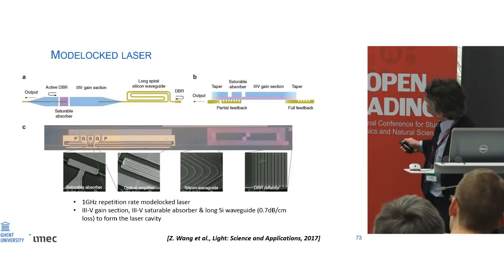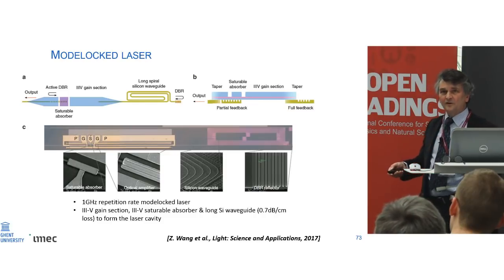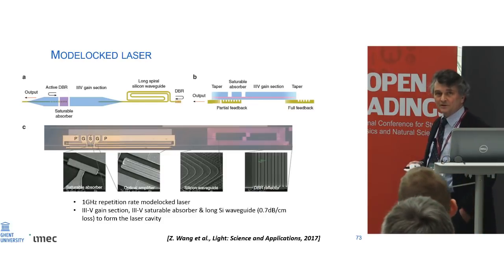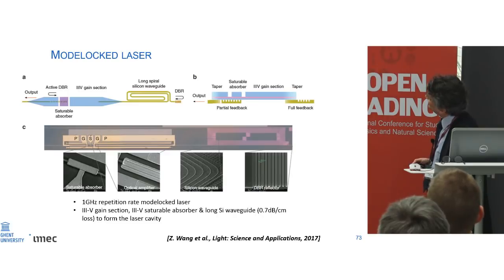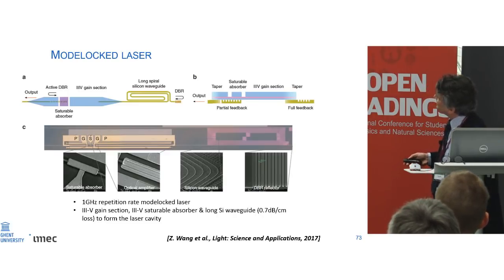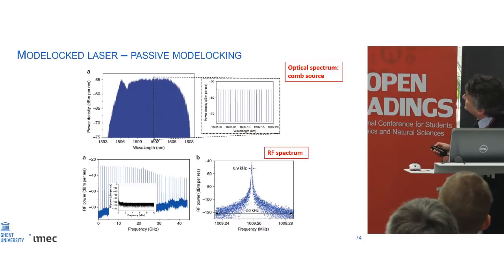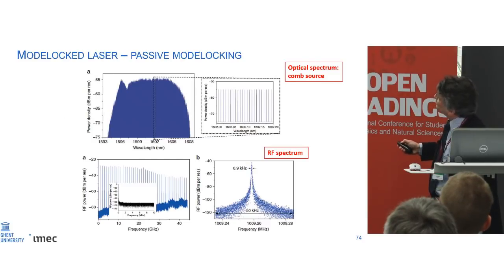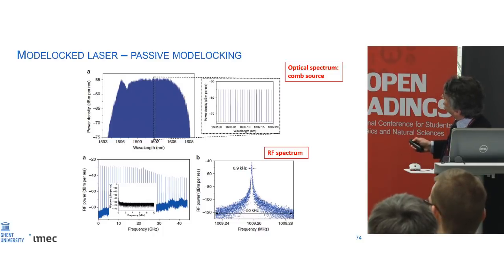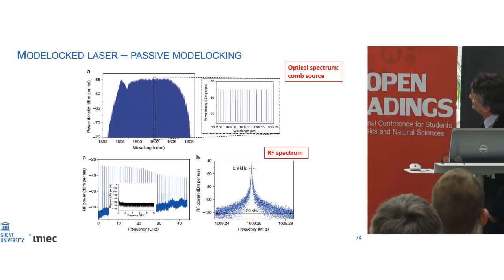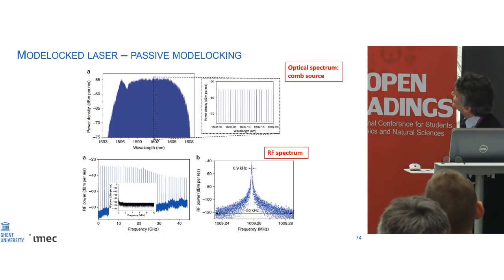Probably a few millimeters or centimeters long, I don't remember, which is in the silicon waveguides. The losses in silicon waveguides are considerably lower than in III-V waveguides, so that boosts the performance of these mode-locked lasers. And here you see the III-V device. And this really works very nicely, and we have a beautiful mode-locked laser where we have many, many thousands of individual lines in the spectrum of this mode-locked laser. And actually a very, very pure phase noise spectrum. This is a comb laser.